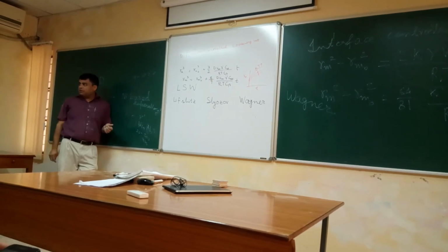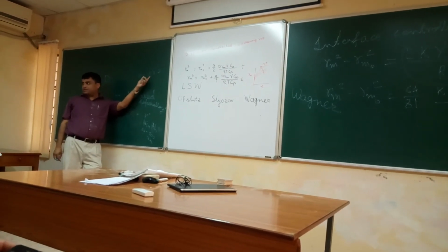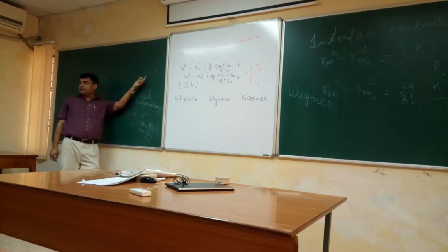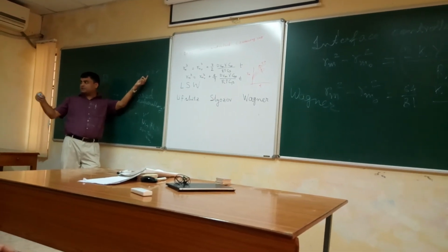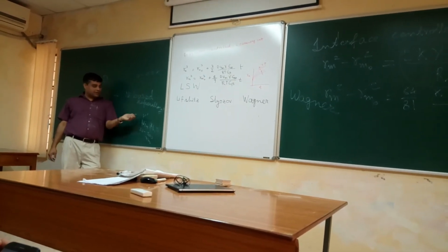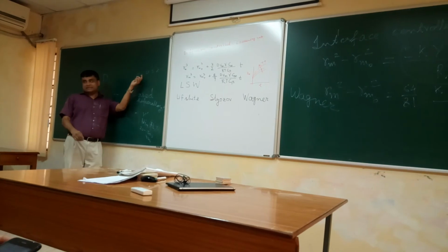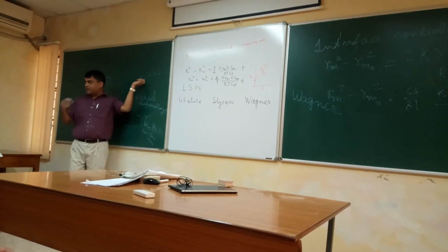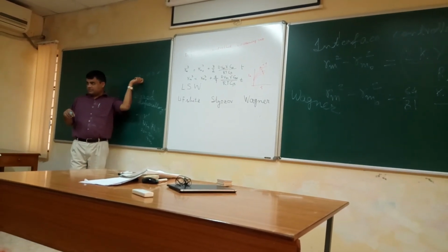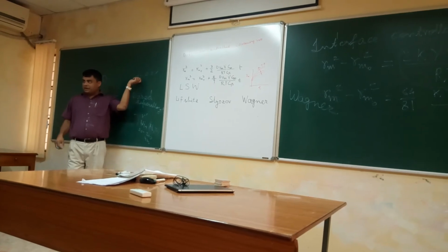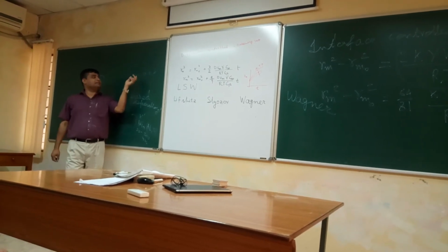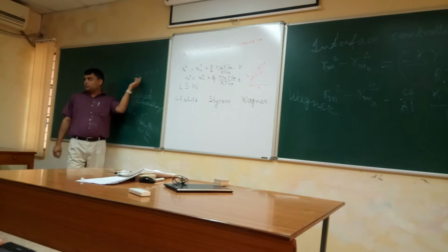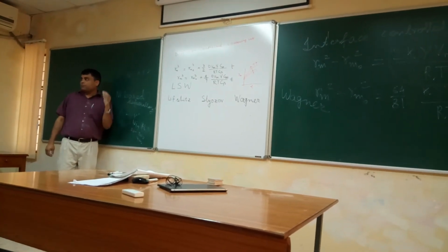It has been found that, instead of 0.2% lattice misfit, this lattice misfit is a function of alloying elements. So you put certain alloying elements, you engineer it such a way that your lattice misfit goes to near 0 from 0.2.